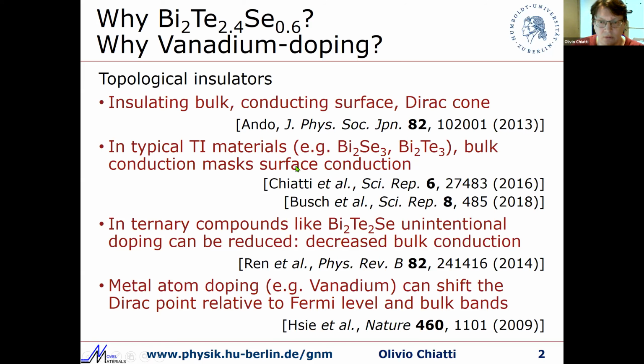We have seen in our own work on bismuth selenide that in these typical materials like bismuth selenide or bismuth telluride, unintentional doping of the bulk can provide bulk conduction states which mask surface conduction. So it becomes difficult in transport measurements to detect and identify topological surface states.